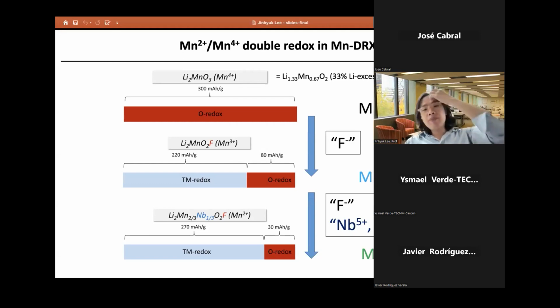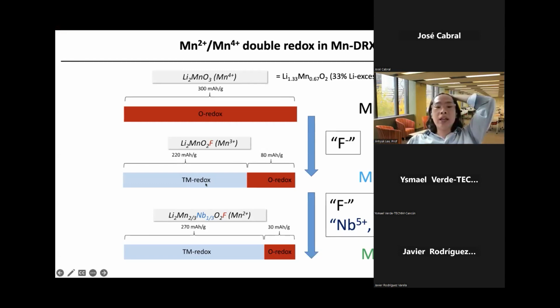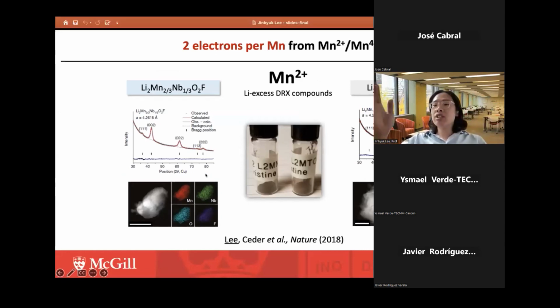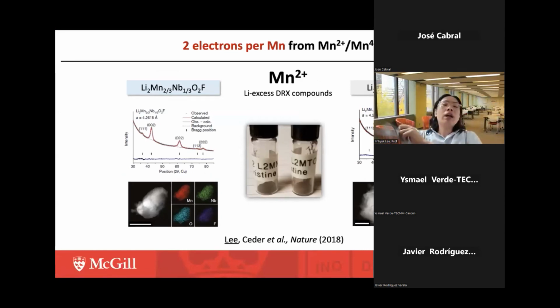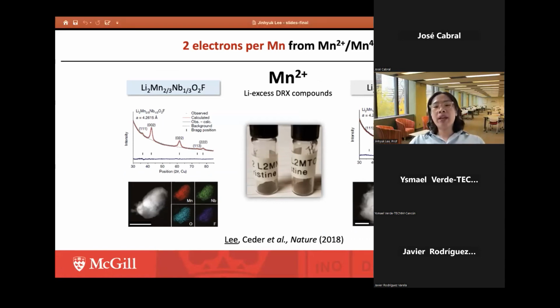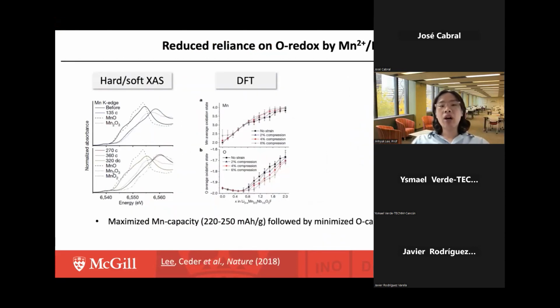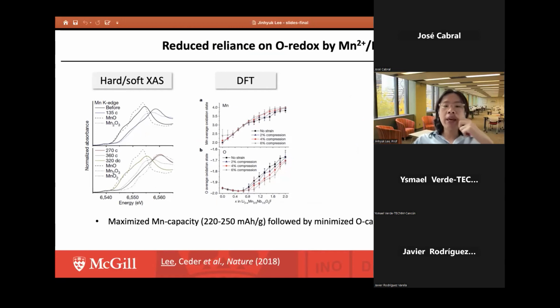So based on this idea, we went into the lab and synthesized 2 different types of manganese double redox compounds, which are lithium manganese niobium oxyfluoride and lithium manganese titanium oxyfluoride with this particular composition. And this material can utilize 2 electrons per manganese atom. Because the manganese oxidation capacity in this highly lithium-excess material is large, we found using hard and soft X-ray absorption spectroscopy and density functional theory calculations that the oxygen oxidation capacity is minimized.